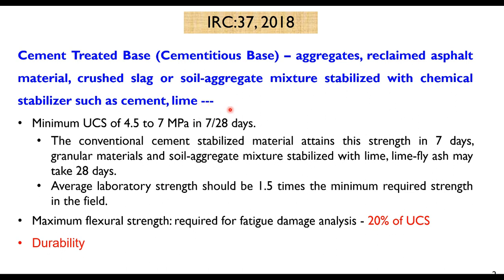The requirements as given in IRC code for a stabilized base are that the minimum UCS — unconfined compressive strength — should be 4.5 to 7 MPa, and this strength can be achieved in seven days in case of cement stabilized material, whereas it may take 28 days in case of soil aggregate mixture stabilized with lime, lime fly ash, or other stabilizers. The code also suggests that the laboratory strength should be 1.5 times the minimum required strength in the field.